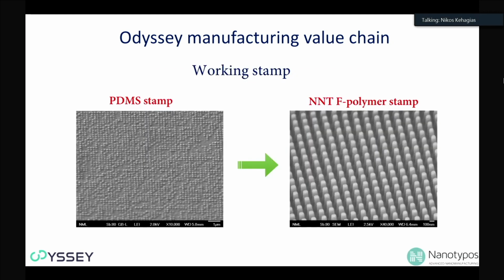Going into the working stamp, the first material we thought could potentially replicate these kinds of features and from holes achieve pillar structures was PDMS, but that was not really the case. PDMS is a nice material that could be used for micro replication or sub-micro replication, but in our case, because we had high aspect ratio structures, very small in diameter, we were not getting a very good replication fidelity by using a PDMS stamp. So that's when we started looking at what is in the market in terms of materials which could be used as a flexible mold. And we were not really happy with what was in the market. So we started developing our own fluorinated, UV curable polymer material. And we were very successful in getting very, very nice results of replicating our silicon master stamp.